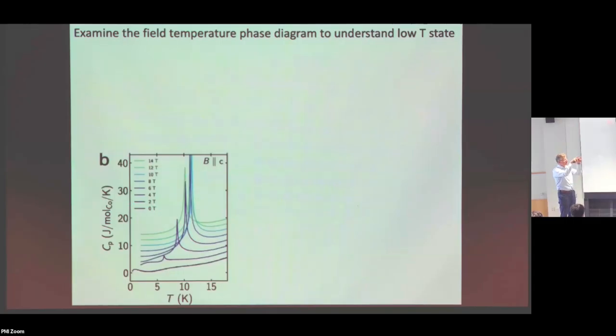that's when we do have these six little dots. And so we do have some fairly long range correlations, but there's no peak indicating a phase transition. These are all just kind of broad features in this specific heat. And that's not because of disorder or not good samples. Samples are excellent, but it's because this is actually not a second order phase transition. It's a two-dimensional system which has a Kosterlitz-Thouless type phase transition. And so these broad peaks are all that's left to indicate that there is actually a phase transition going on, but it's of the vortex unbinding type.